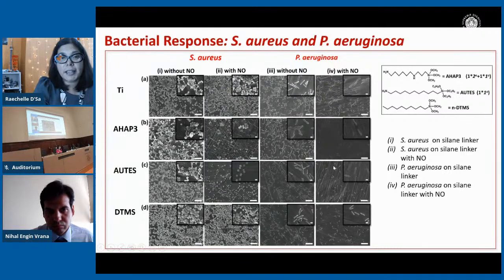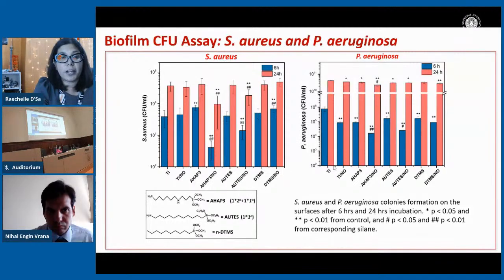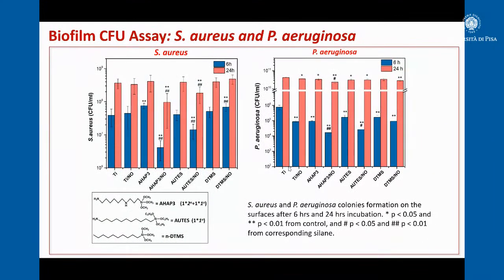So if we look at the biofilm CFU response, so we look at numbers specifically of what happens. We've looked at Staphylococcus aureus and Pseudomonas once again, and we've looked at it after 6 hours and after 24 hours of adhesion. So what we find is that for our surfaces with no capability of nitric oxide, we don't see a decrease in bacterial response, as expected. But for our surfaces with the aminosilane that have the ability to tether nitric oxide, we see, for example, the AHAP surface, we see that there is a 1.5 log reduction in the amount of Staphylococcus aureus after 6 hours compared to the silanized surface.